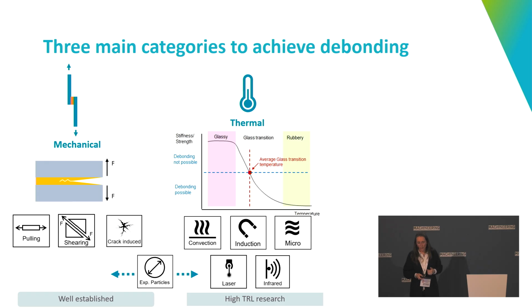But sometimes there is a little bit more technology involved, and we can use thermal triggers. With thermal triggers, we will play with the temperature. Quite often we increase the temperature above the glass transition temperature of our adhesive. How we do it doesn't matter. It can be with convection, induction, infrared. But when we increase the temperature above the glass transition temperature, then our adhesive becomes weak and we can debond the components quite easily. And we can have an extra aid in this with thermal expandable particles. These are particles that we add to the adhesive, and under the influence of temperature they will swell, and in that sense also apply a mechanical force on the bonding line, and they will let your components debond. There is still research going on this, but it's high TRL research.